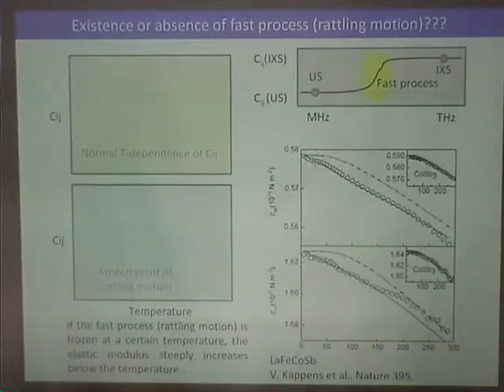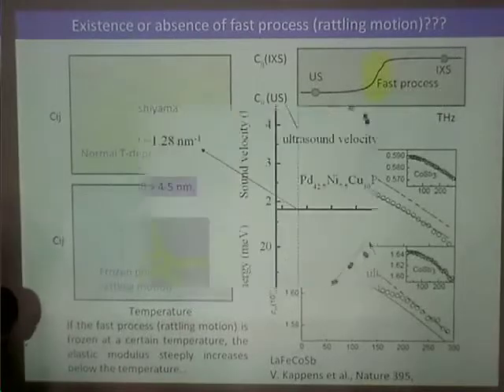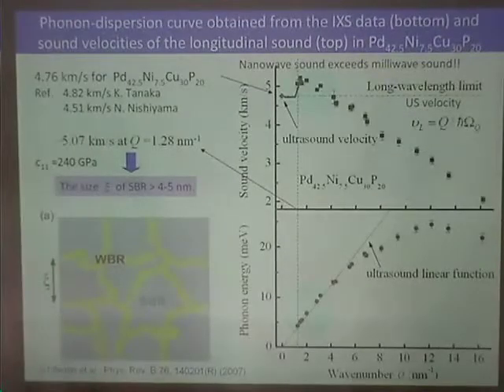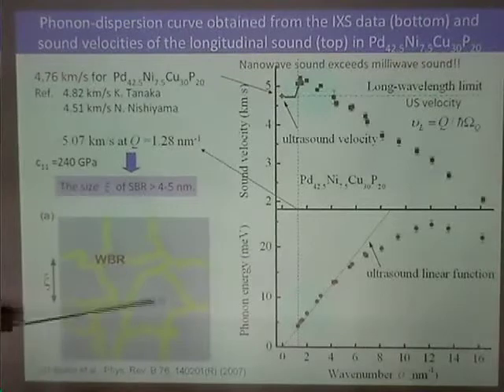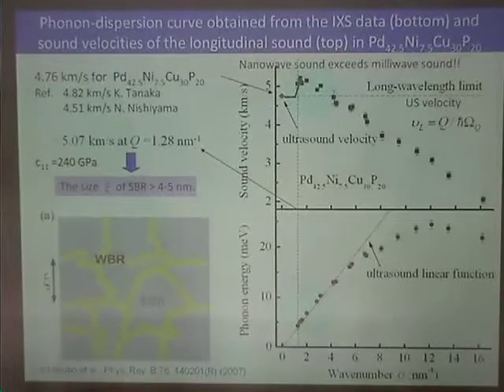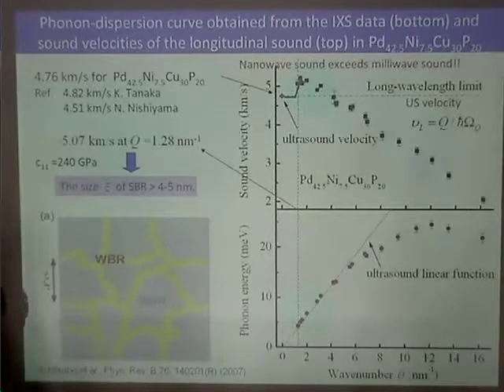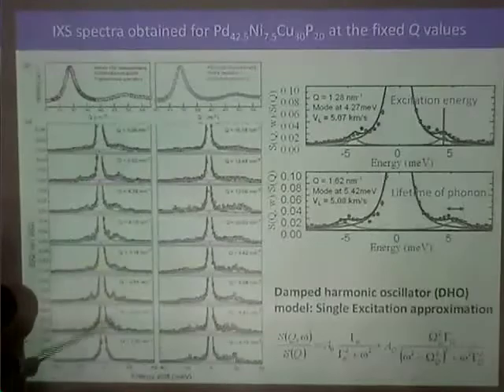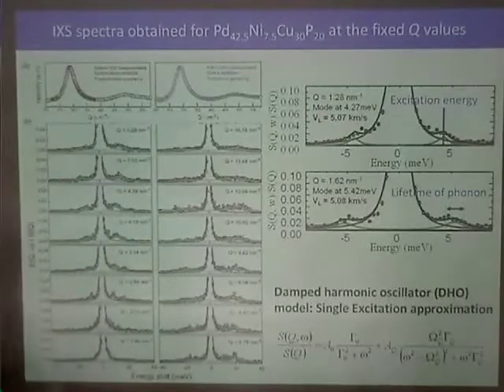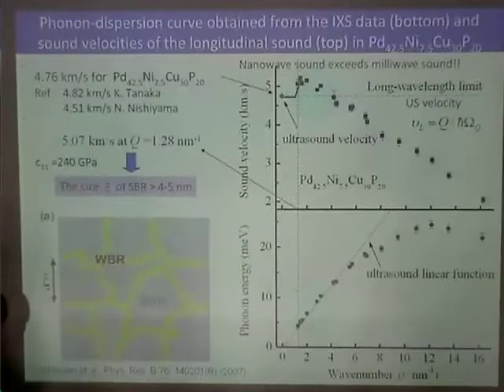So therefore, in that experiment, we probably have this strongly bonded region that has a much higher elastic constant. So a slightly higher elastic constant exists in the glass substance. Therefore, in order to check that this is valid, we have to exclude the time-dependent phenomena.